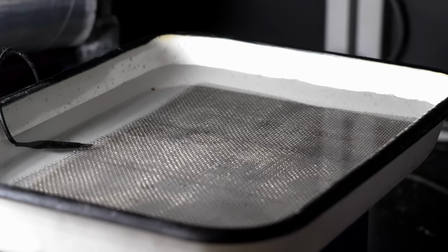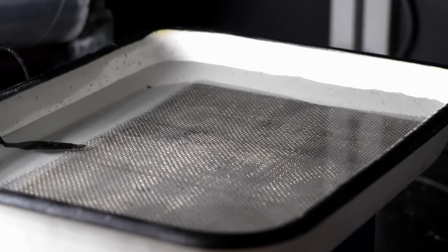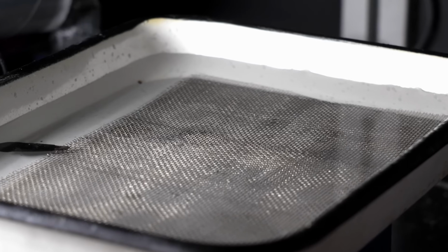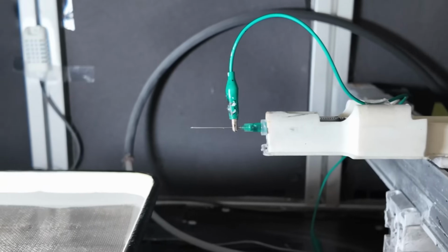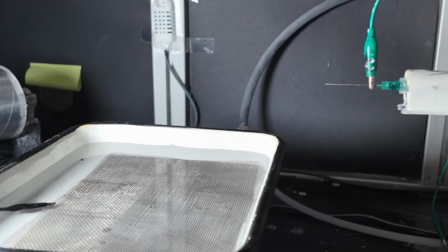Applying a voltage of 10 kilovolts, we create a high potential difference that makes the cellulose solution squeezed out of the syringe atomize and spiral into fine filaments, which are subsequently deposited on the water surface. Similarly to the previous experiment, the ionic liquid dissolves in water, and the resulting cellulose microfibers remain in the form of a fine precipitate. This process is called electrospinning. It allows the production of ultrafine fibers, which are subsequently used in the latest medical research on the creation of artificial skin. The only trouble is the process takes about an hour because our machine is far from industrial.